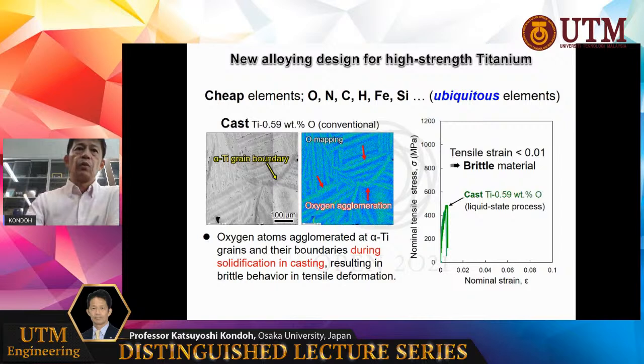For example, in the traditional casting process, they added about 0.59 weight percent oxygen into titanium. In such a case, as shown in these EPMA results, there is agglomeration of oxygen atoms at some grains or at some grain boundaries. This oxygen agglomeration causes brittleness of titanium materials.